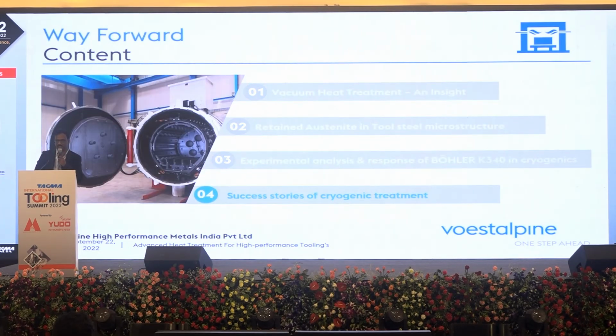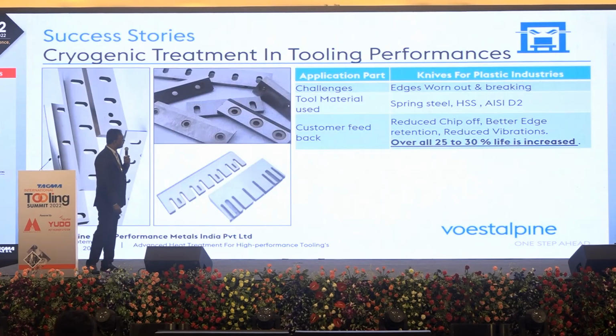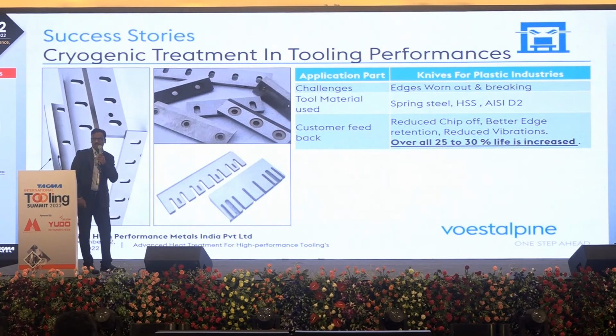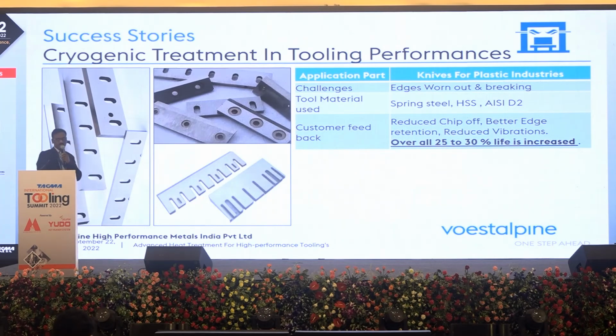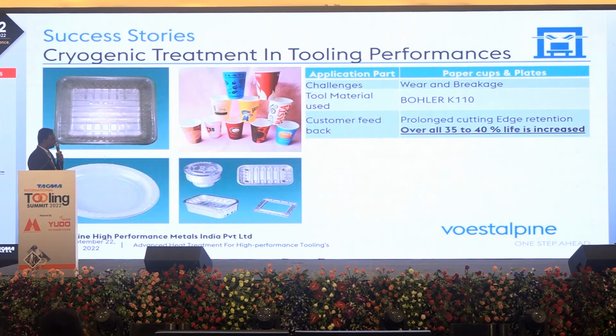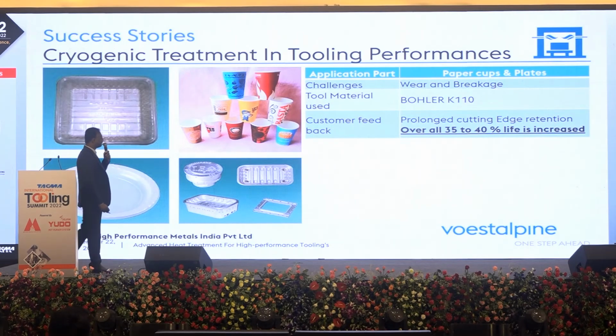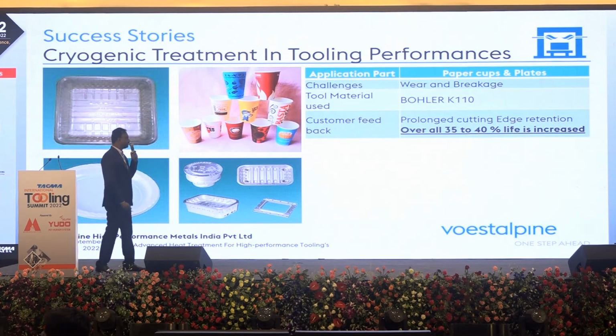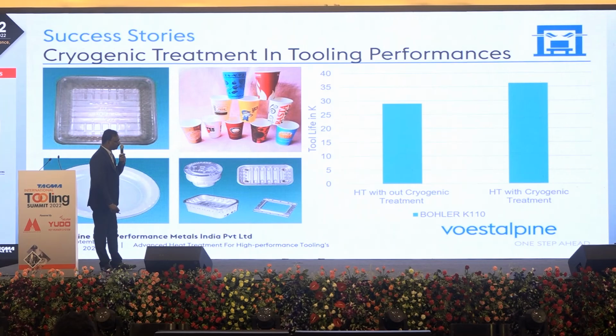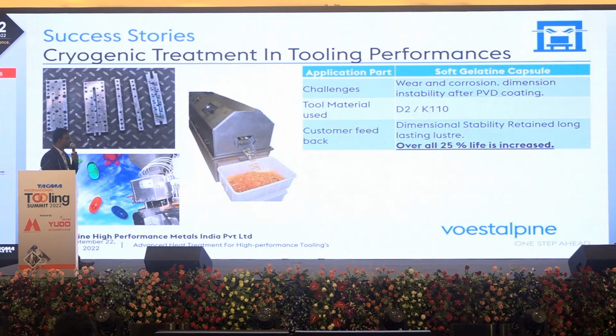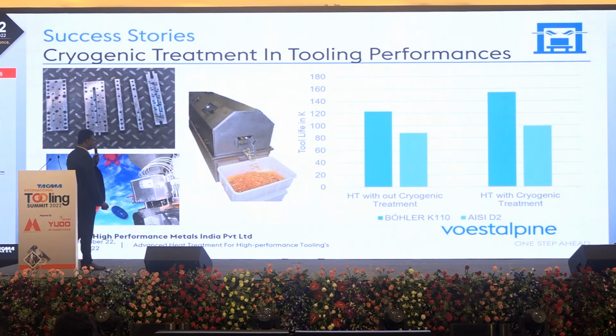The final, last but not least, the success stories. The success stories of cryogenic treatment. If you see the knives, the failure mode is wearing out and breaking, and the life performance increased by 25 to 30% by doing cryogenic treatment. This is again from BÖHLER K110. The application is plastic paper cups and plates. The performance increases 35 to 40% with BÖHLER K110. This was soft gelatin capsule machine elements made out of AISI D2 and K110, and the overall percentage increase is 25%.